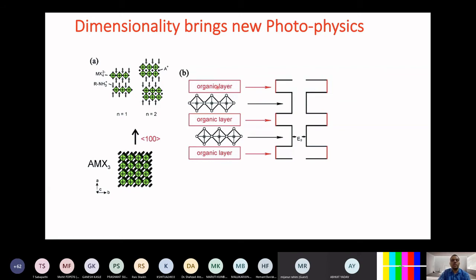So these are very good on the B side. And if you want to see it on the energy scale, you have the inorganic with the lower band gap, separated by the large band gap semiconductor. So you have sort of a gallium arsenide, aluminum gallium arsenide kind of stack: gallium arsenide low band gap, aluminum gallium arsenide large band gap. The same way here, you have the organic layer with a large band gap close to 3 to 4 electron volts, even higher, and then you have the perovskite with the lower band gap, depending on whether you have a single layer, a double layer, or a triple layer. That will decide the change in the band gap.